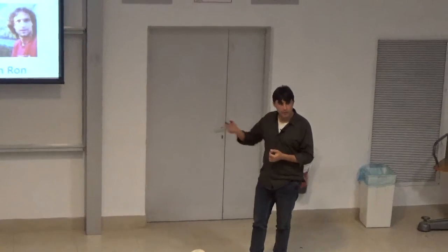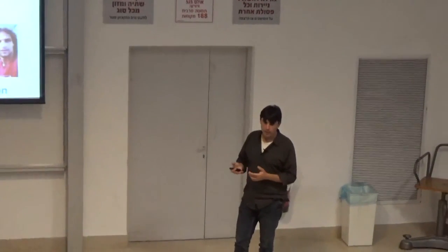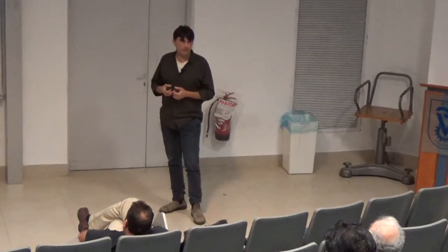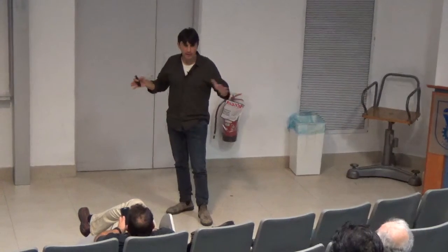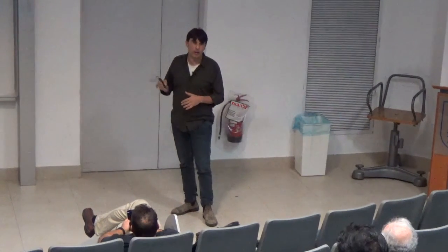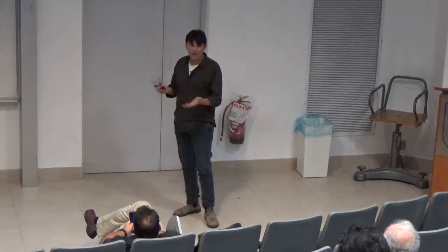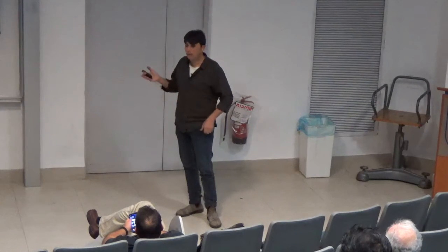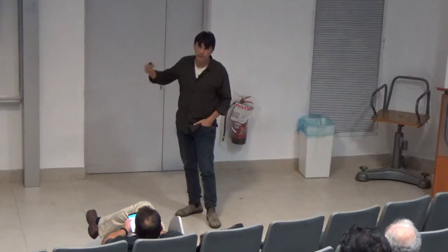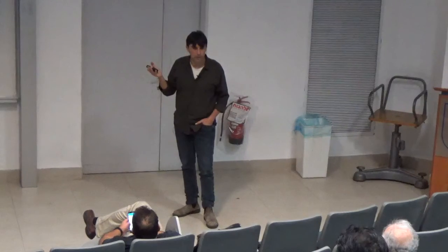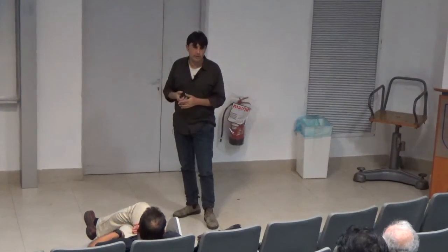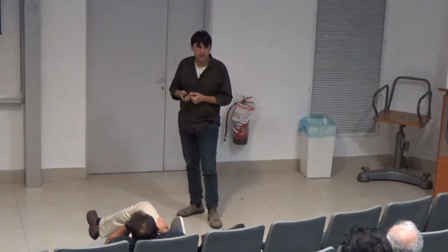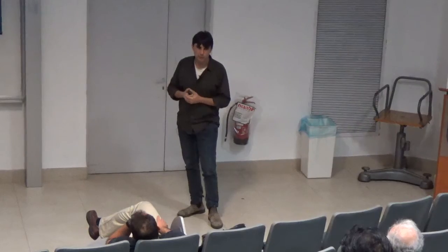If you compare it to the mean-free path in this material, mean-free path is like 1,000 angstroms if you're generous. And if you look at the phase coherence length in the 2-dimensional system, it's about 1,000 angstroms too. So this is larger than both length scales, which is also surprising. But for some reason, it's working. So there is some kind of protection against backscattering. We interpret that as a result of magnetism and spin-orbit interaction, but this is still to be studied and understood.